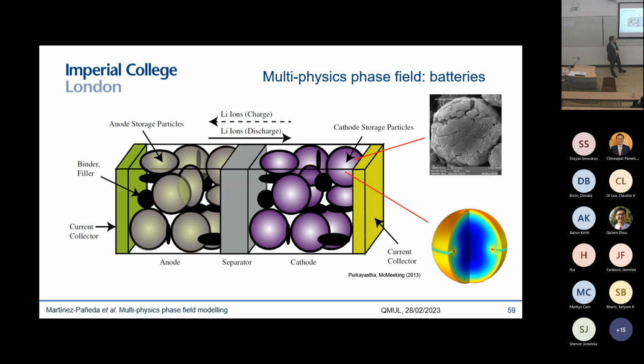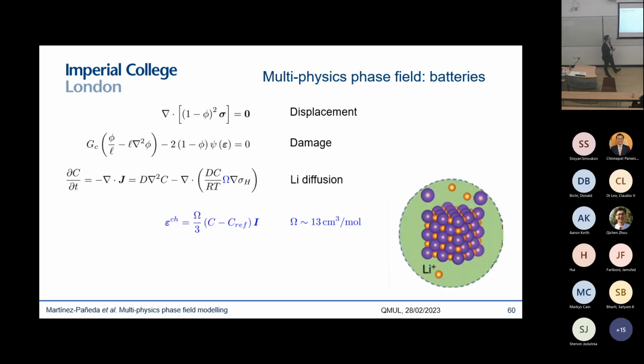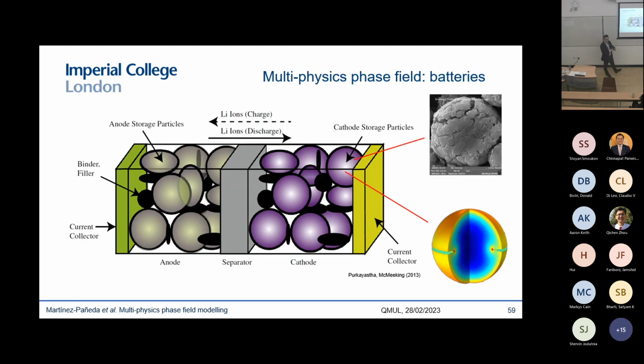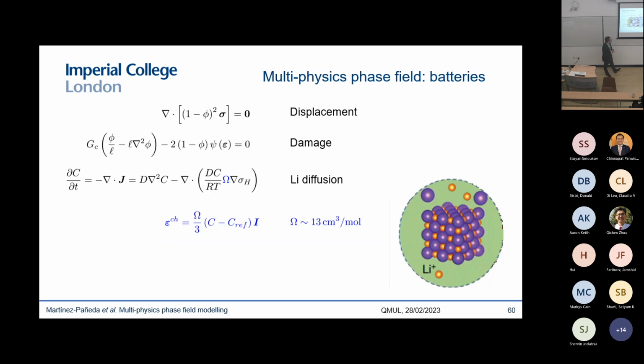So what we try to do is use these multi-physics phase field fracture models to map under which conditions of charging and material properties we will see these cracks appearing. We wanted to do so also for fatigue, because a number of people have developed phase field models for electrode particle cracking, but they were only looking at one charge cycle, and we want to do it for multiple. This is, of course, a cyclic problem.